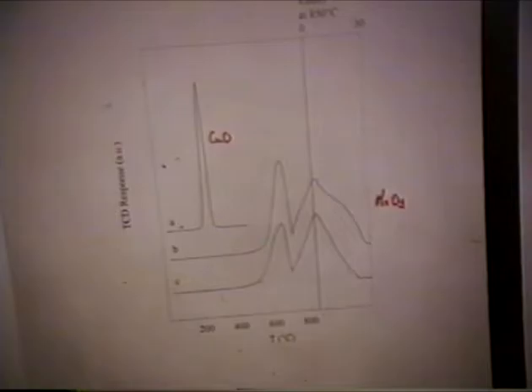As background, we're looking at the thermal decomposition of commercial molybdenum-6 oxide. You get two peaks: one on the initial reduction of moly-6 to moly-4, and then on the second reduction of moly-4 down to moly-0. We looked at the material, the ammonium heptamolybdate that we heat treated in nitrogen at 500 degrees C, and we got the same type of thermal decomposition spectrum.